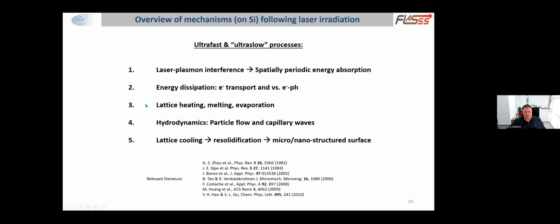After some time, and provided that the energy of the laser pulse is enough, we have lattice heating and melting, and even evaporation if the energy of the laser pulse is very large. And of course, one needs to take into account hydrodynamics in order to describe the particle flow and capillary wave formation. And after a long time, by long I mean time in the order of nanoseconds or microseconds, we have the lattice eventually cooling down, and we have the surface resolidifying, and we end up with a surface which is